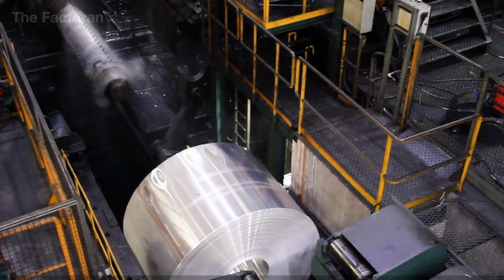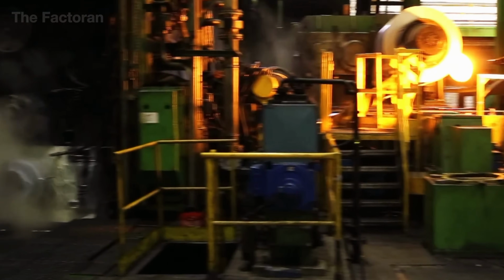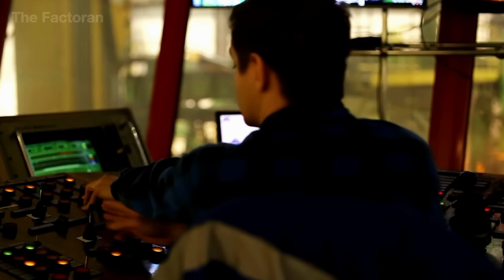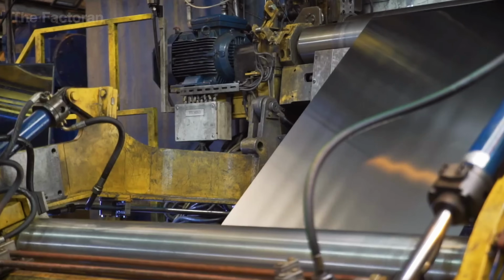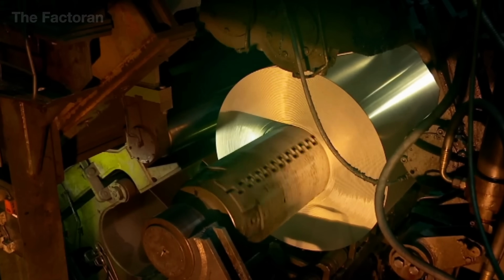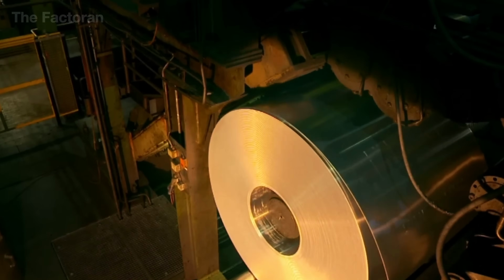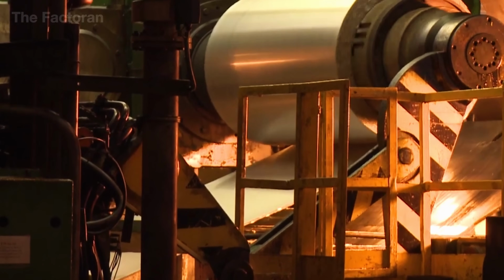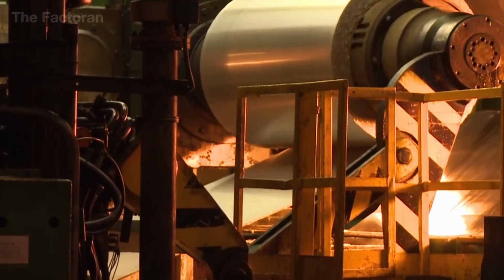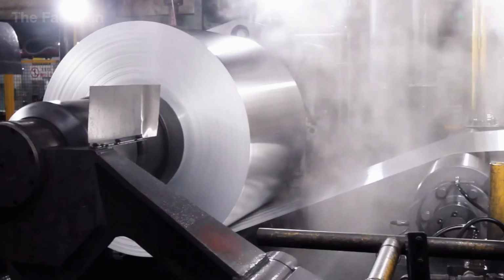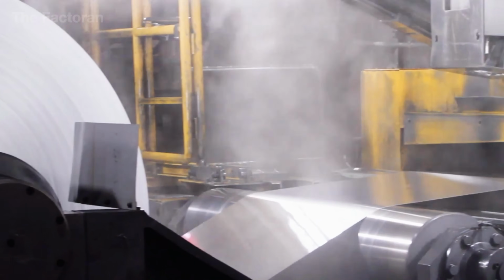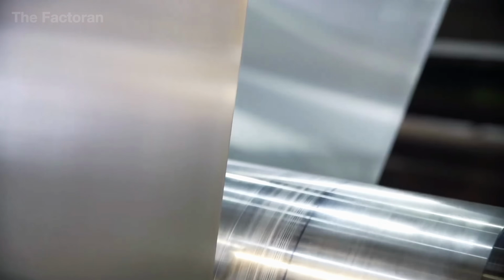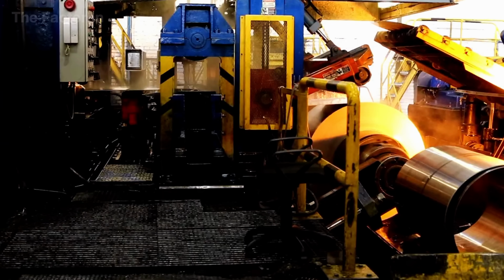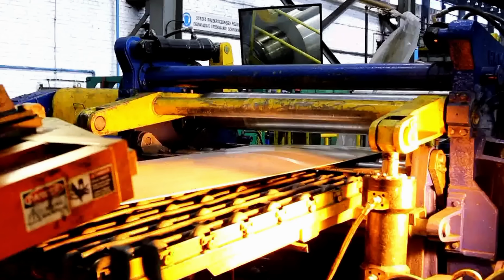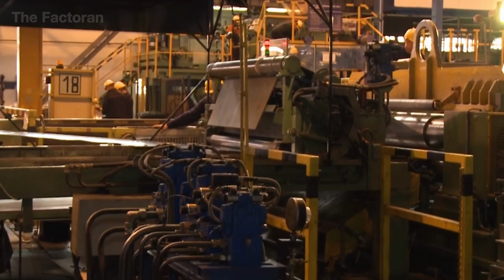Have you ever wondered why aluminum foil has one side that's shiny like a mirror and another that's duller and matte? The answer lies in the very last stage of cold rolling. After multiple passes through huge steel rollers to thin the aluminum, the final pass is done with two sheets stacked together to save time and boost output. The outer sides, pressed directly against the rollers, are smoothed and polished, giving them that signature shine. The inner sides, touching only aluminum, retain a slight texture and appear matte.